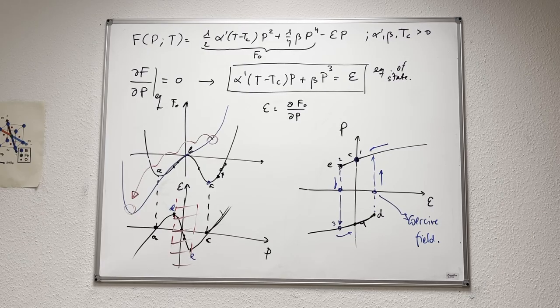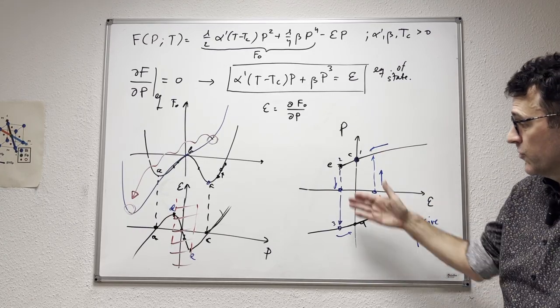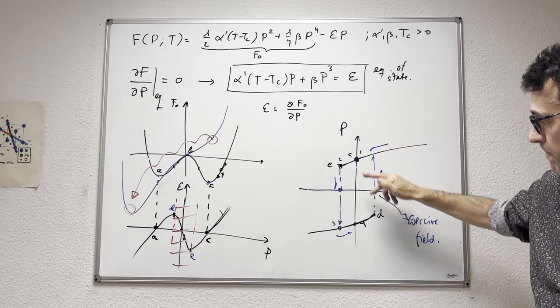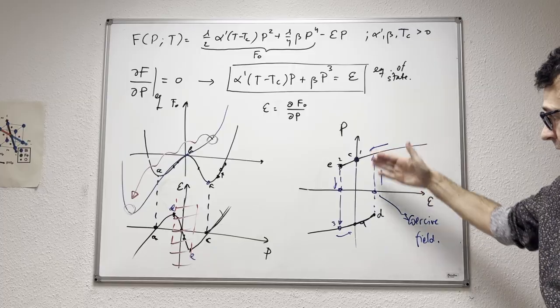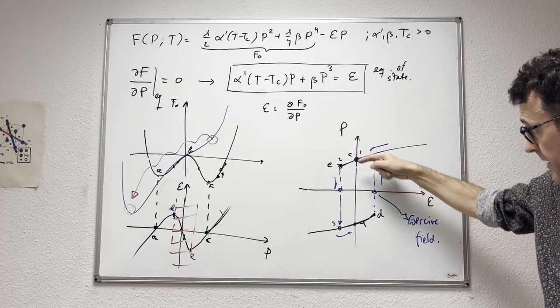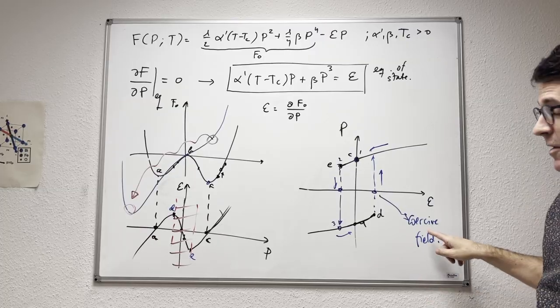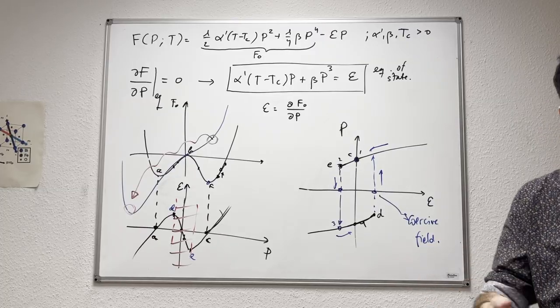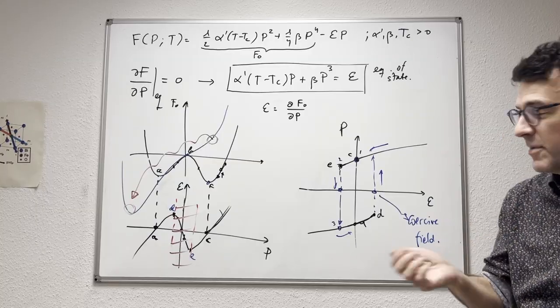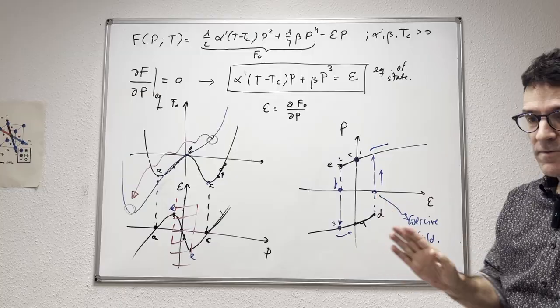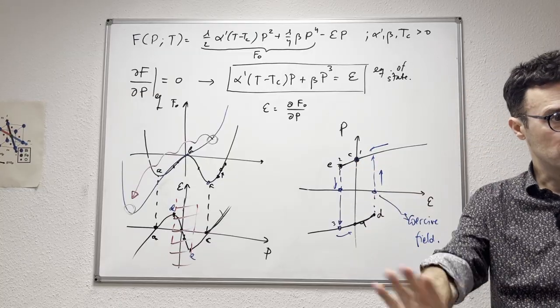And essentially this is it. Then what is cool also is that, if we think about this coercive field, you see that in the hysteresis loop like this, there are several outstanding features, right? There is the spontaneous polarization that we have at 0 field. And then there is the field that I need to apply to force the phase transition. In practice, the transition may happen before this theoretical coercive field, as we know, because there is thermal activation, because things may happen a bit earlier. But we know that if we are at the coercive field, something has to happen, because we lose the minima.